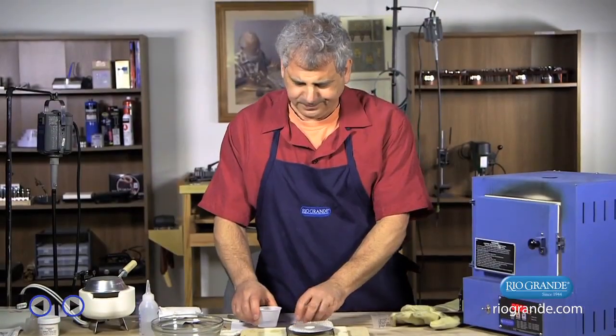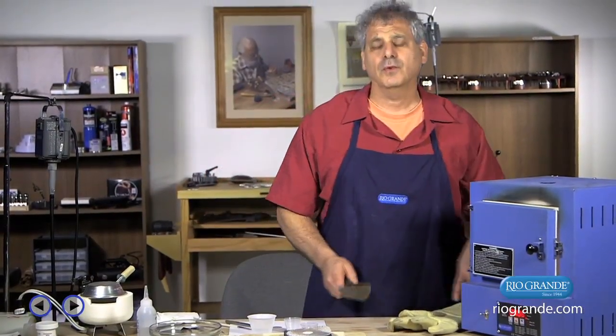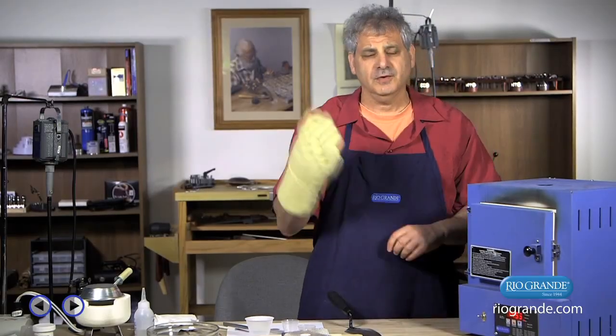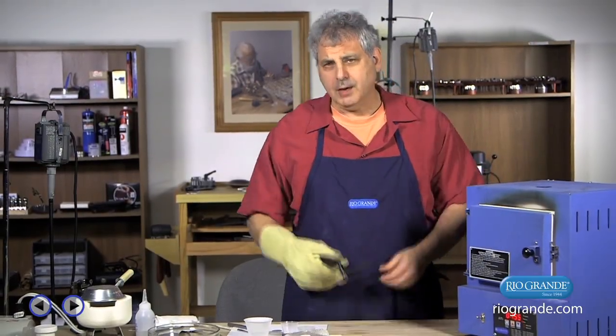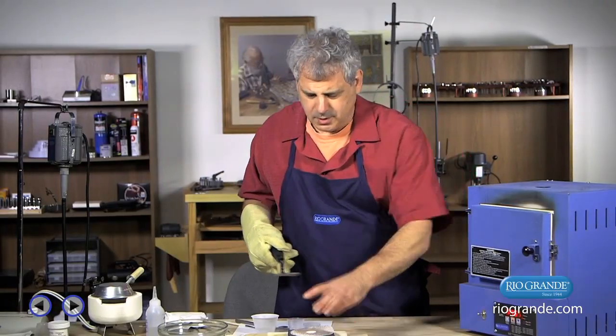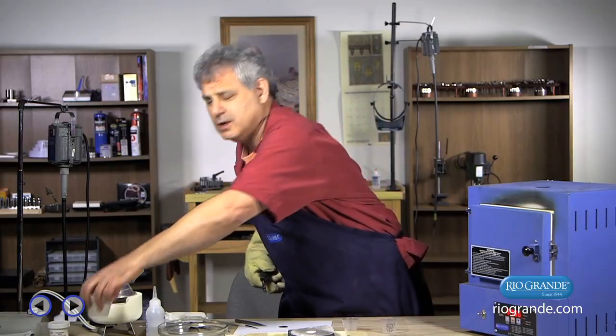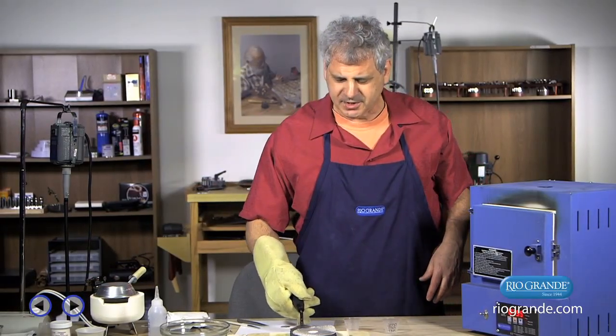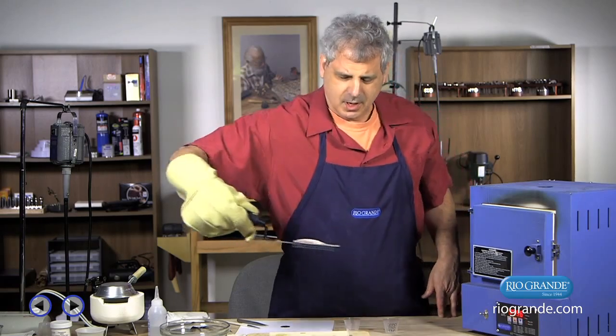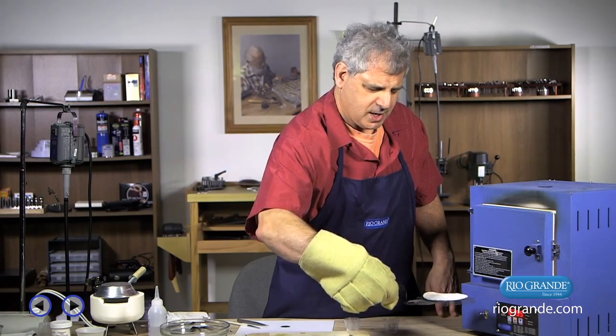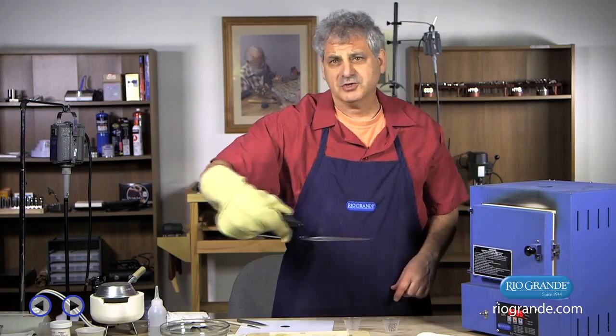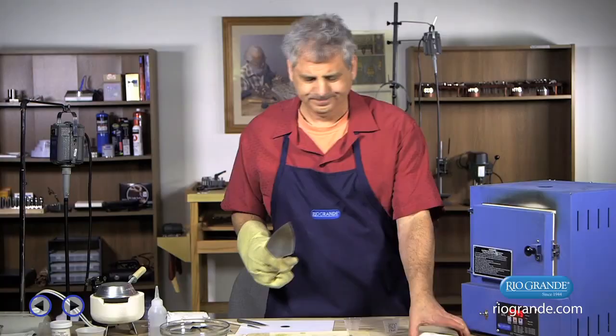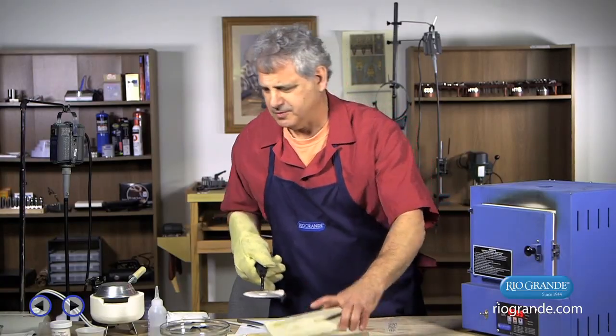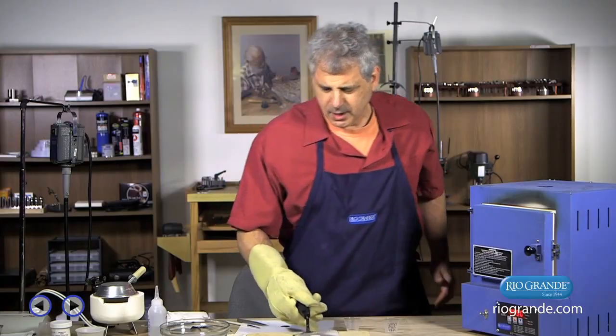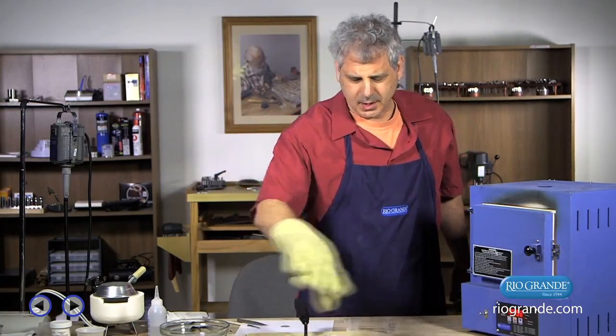So I'm going to put it in the kiln here, and I'm going to fire this enamel around 1300 to about 1450 degrees. I'm going to use a glove because this kiln's going to be hot when I open this door. I'm going to use a trivet. I'm going to move my water because I always spill my water if I don't get it out of the way. I'm going to slide this in. I'm going to lift it straight up. I'm going to go straight in. I'm going to lower it straight. And then I'm going to remove my trivet straight so that I don't knock it over. And actually I can just remove this now too.